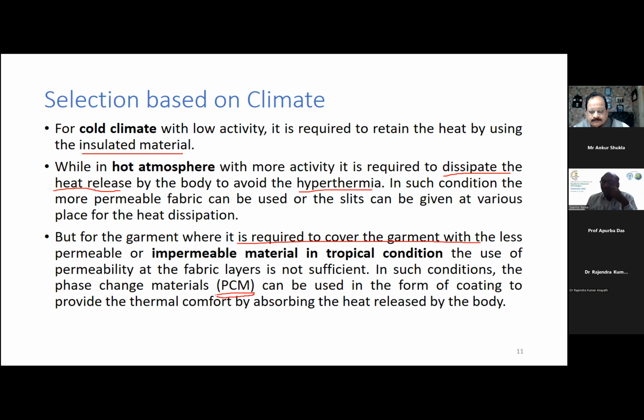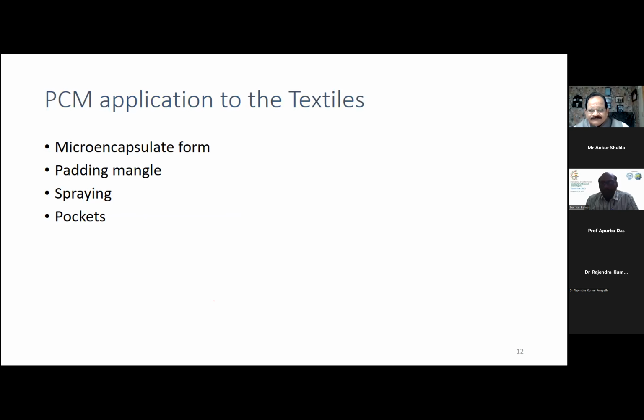So these can be used in the form of a coating to provide thermal comfort by absorbing the heat released by the body. That is what we have done, sir, here, Vijay sir. It is basically done with either the microencapsulation technique, padding, or spraying, or by keeping ice packs in the pocket. The pocket application is simple, but it will create a lot of discomfort. So here we have gone with the coating technique. We have selected a proper binder and a commercially available product, but not for textiles. We have taken that and added the proper binder, and then we have tested the fabric for how it is functioning.